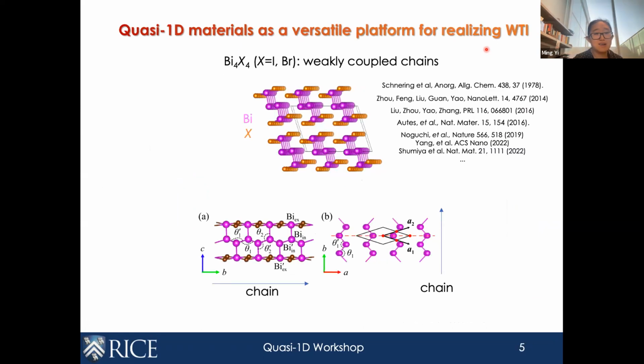This is why, as Fan already described, many groups are attracted to quasi-1D materials, as demonstrated by the Bismuth Halides, because they're weakly coupled chains, and that means two things. One is that you can realize a variety of stackings that can give us different types of novel topological states. And practically, when they're weakly coupled chains, we can easily cleave different surfaces and therefore look at a surface-dependent measurement of the topological surface states.